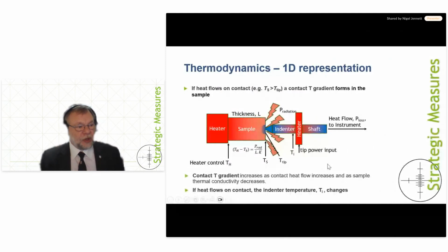If heat flows on contact, then you'll get a change in this gradient here, and you'll get a change in the temperature that you measure here. And so by going into contact and seeing if that changes, you can detect whether there is heat flow.